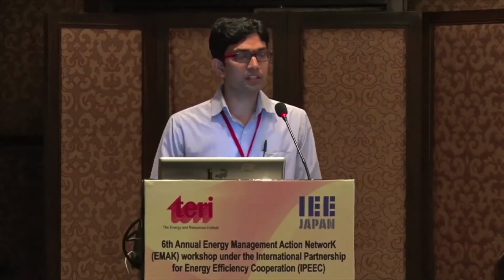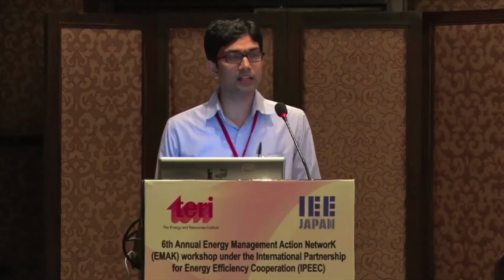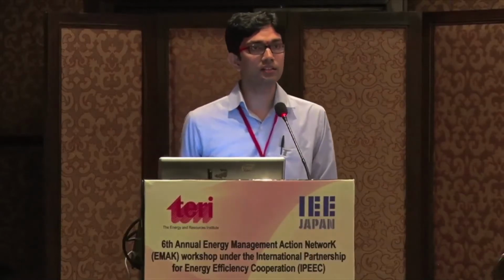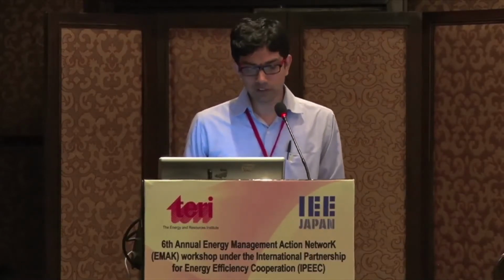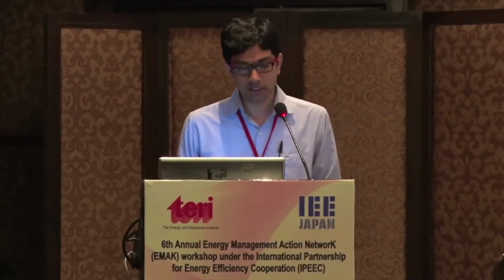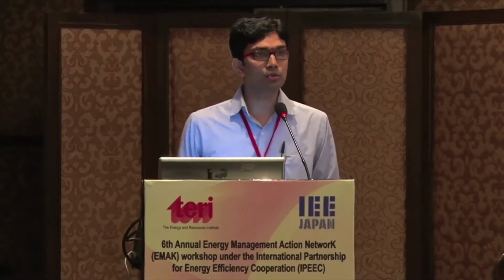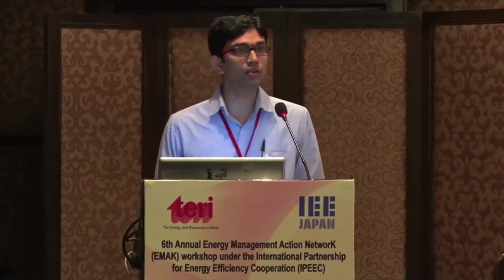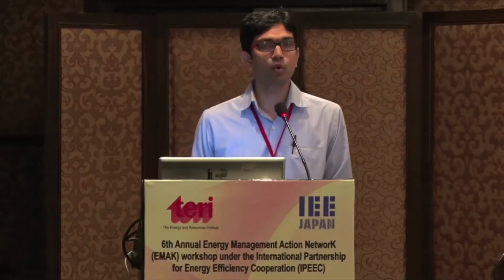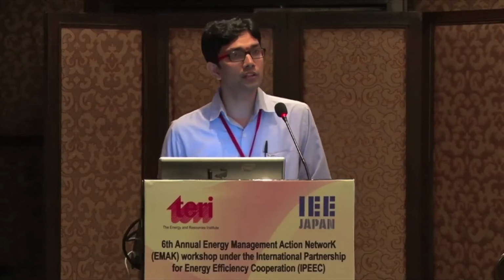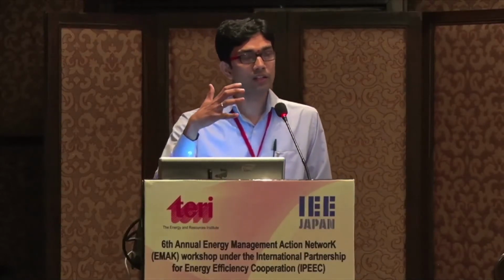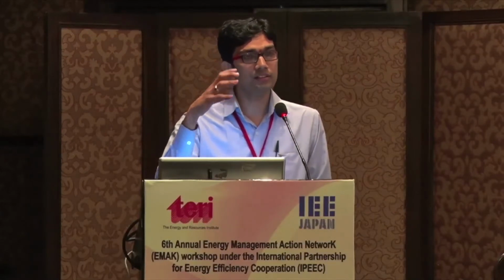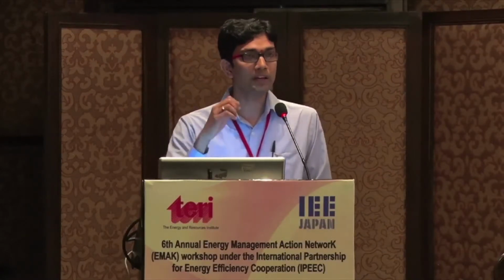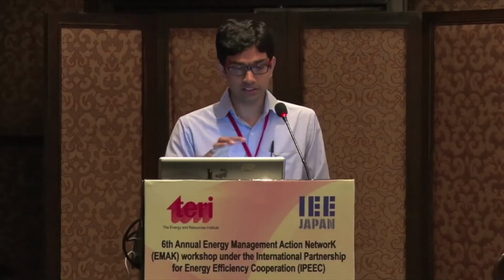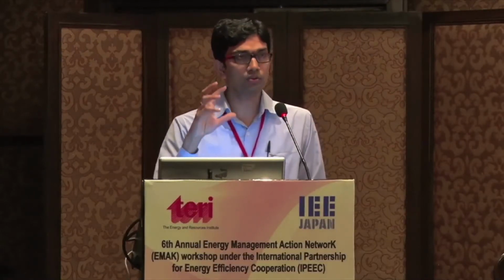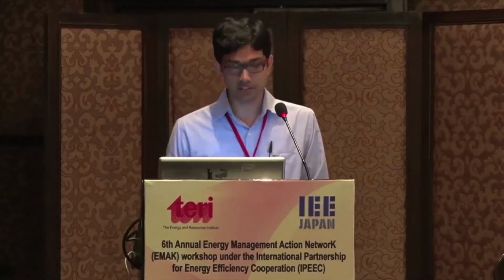Coming back to the subject of waste heat recovery, you would find on the left side again, there is a box-type cylindrical structure which they call a waste heat recovery system. And this is primarily to preheat the furnace oil that is going into the furnace. This is more out of desperation of preheating the furnace oil to save jamming of fuel during winter and to make it more viscous during winter season. So this is a case not to save energy, but an operational measure.